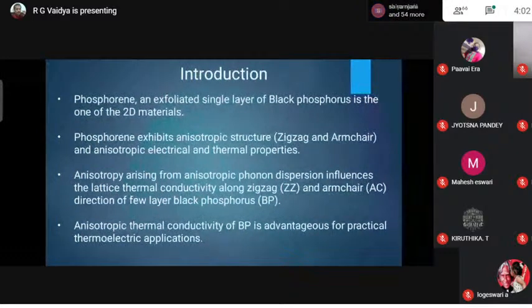We have done the theoretical work on the phosphorene, that is the exfoliated single layer black phosphorus, which is one of the 2D materials. Phosphorene is observed to exhibit extraordinary properties such as anisotropic structure, and anisotropic electrical and thermal properties are also observed in case of black phosphorus. This anisotropy is observed to arise from the anisotropic phonon dispersion, which is observed in the zigzag and armchair direction of the few layer black phosphorus.